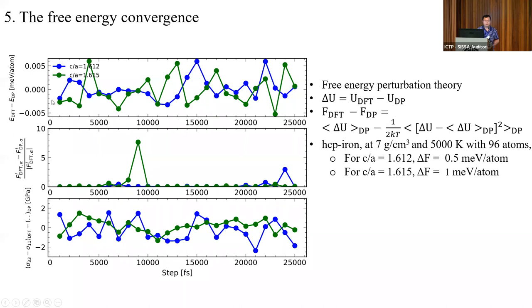The energy difference between the DFT and DP model is well within about 5 meV/atom. Using free energy perturbation theory, the first-order free energy difference equals the internal energy difference, which shows our DP free energy is very close to the DFT result. We can also include the second-order correction related to the standard deviation of the internal energy difference. Plugging in all numbers, the free energy accuracy is below 1 meV/atom, which is very accurate.